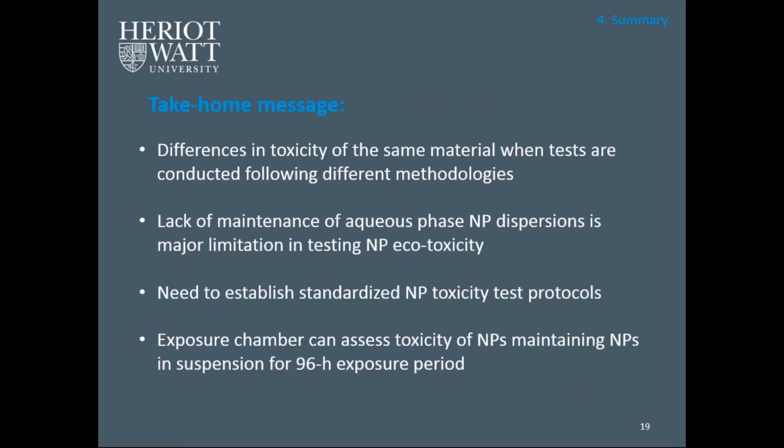So the take-home message is there are differences in toxicity in the same material between different methodologies tested. There is lack of maintenance of aqueous phase nanoparticle dispersions, and that is a major limitation in testing nanoparticle ecotoxicity, and that highlights the need to establish standardized nanoparticle toxicity test protocols. The exposure chamber that is presented in this study can maintain nanoparticle suspension for a 96-hour exposure period.